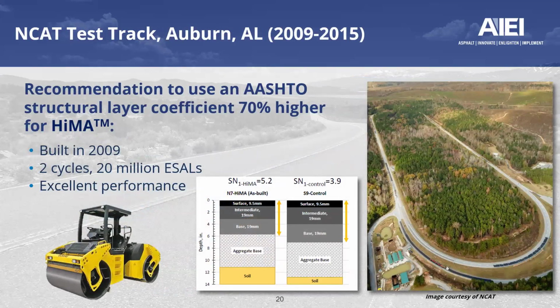Another great example was at the test track for the National Center for Asphalt Technology, the NCAT test track located in Auburn, Alabama. That was one of the first sections built in the United States, back in 2009. The recommendation is to use an AASHTO structural layer coefficient 70% higher when using a certain technology under the high polymer umbrella. The section was subjected to multiple cycles of traffic, and it provided an excellent performance.